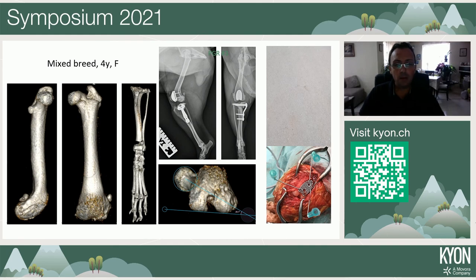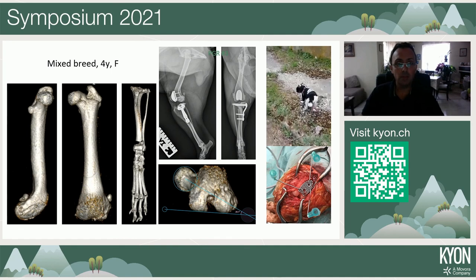That's another case, a little bit bigger animal. This is a Jack Russell Terrier mixed breed dog, where we identified as the reason for medial patellar luxation only external tibial torsion, somewhere about 10 to 15 degrees. So in this case, PGR was combined with TPLO in order to lateralize the tibial tuberosity. And you can also see the dog walking here. That's approximately 1 month after the surgery. So most of the cases recover pretty well, even after such a complex surgery.